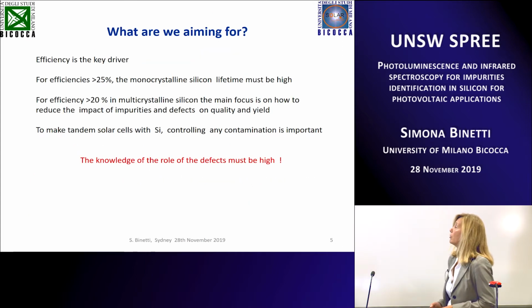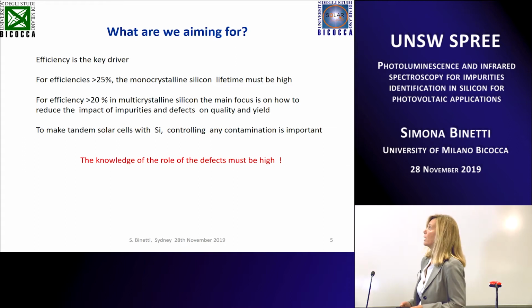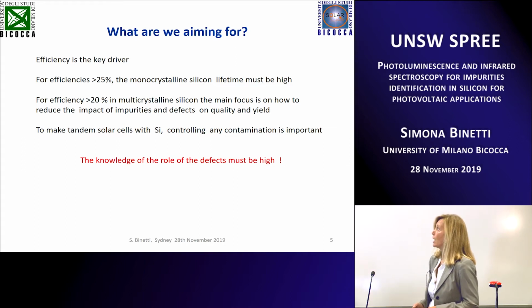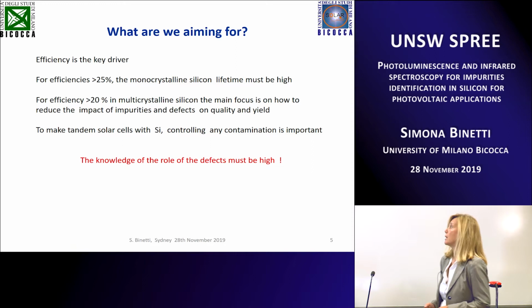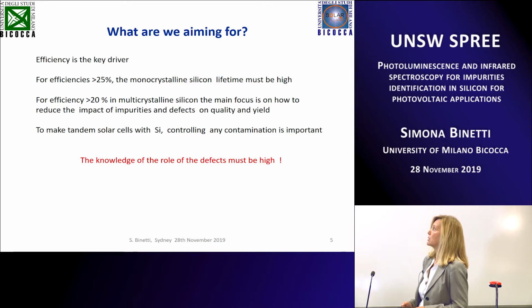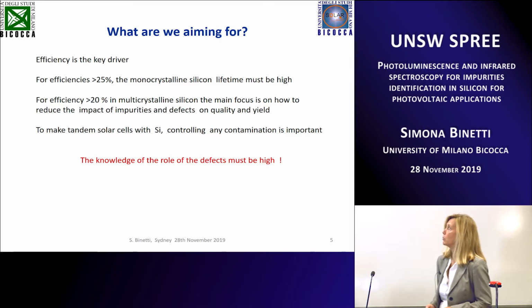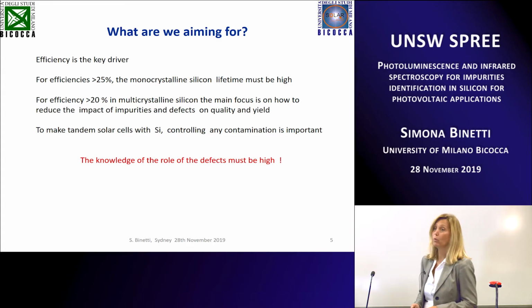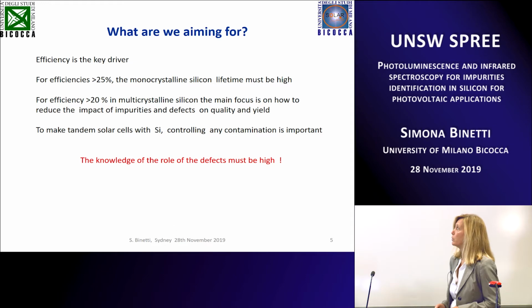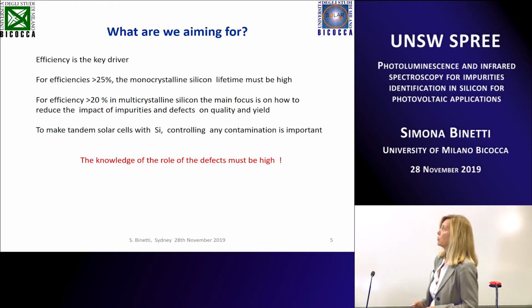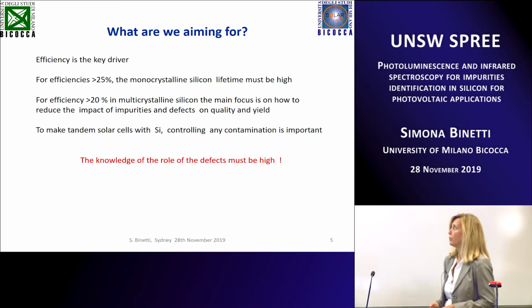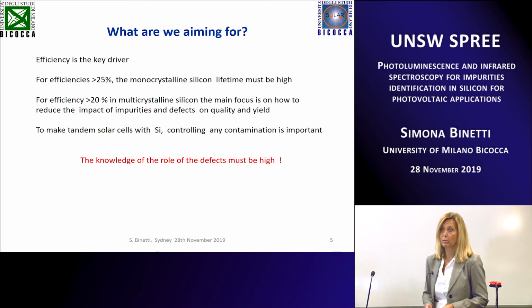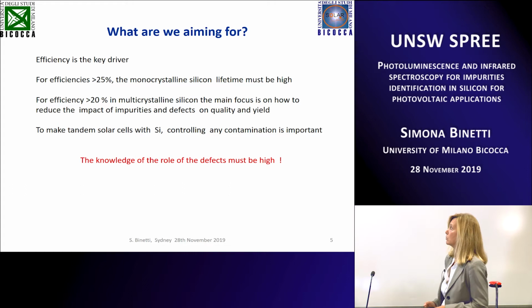What we are aiming for in silicon PV, we know that efficiency is the key driver, but to get efficiencies higher than 25% for monocrystalline silicon and 20% in multicrystalline silicon, it's important to have a better knowledge of the quality of our material. So the impurities, and also in the case of multicrystalline silicon, we have to work to reduce the impact of defects like dislocations, grain boundaries, and impurities related to them.